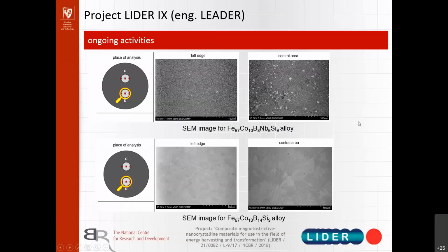If we are talking about the structure of each of those materials, in this 5-element alloy we can clearly see the crystallites, and they are small at the edge, and they are even bigger in the central area. Obviously, it's very related to the production process. The gradient of temperature goes from the outside to the inside, so the highest temperature is on the inside. This is why the crystallites are able to grow.